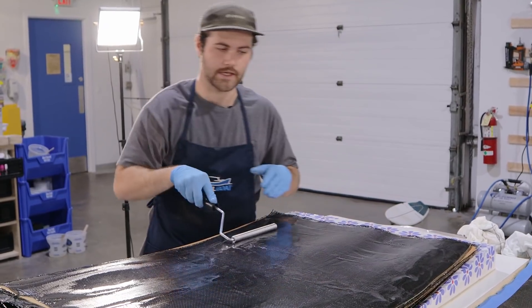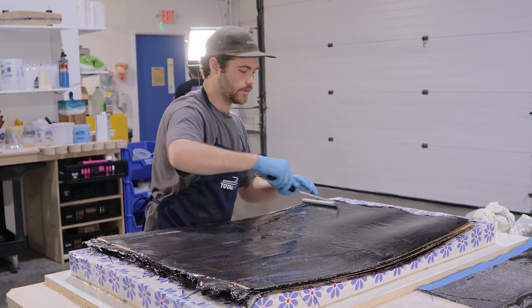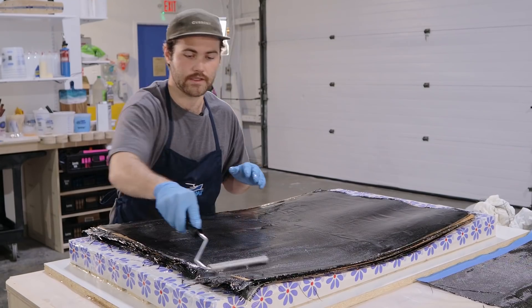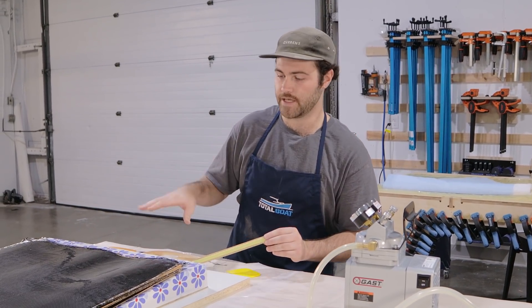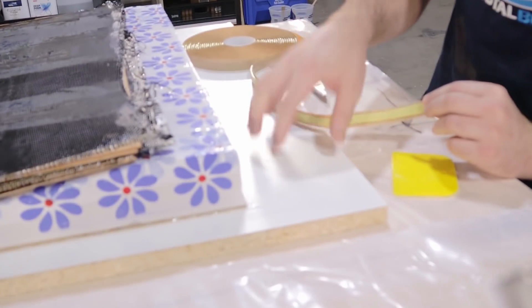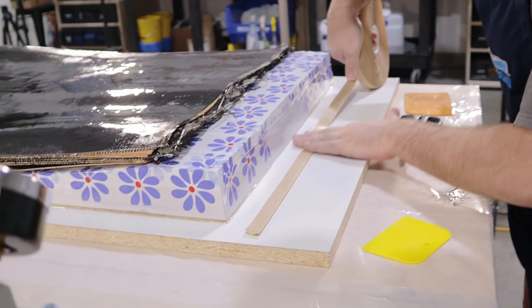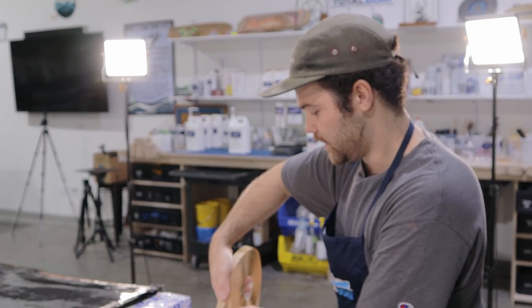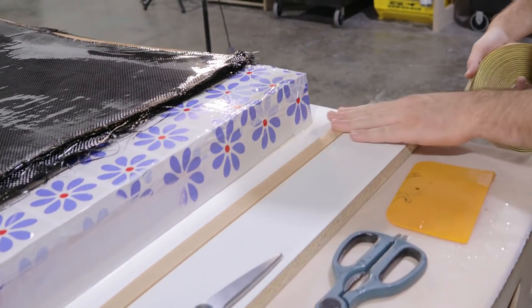We're trying to level out all the resin on this layer. We could get away with squeegeeing it across the other layers since the resin gets squished between the carbon and maple plies, but this layer needs to go down more consistently because we want an even layer of resin for the deck of the board. We've got our gum tape — super sticky double-sided tape made specifically for vacuum bagging — and we're going to tape it all the way around this flange.